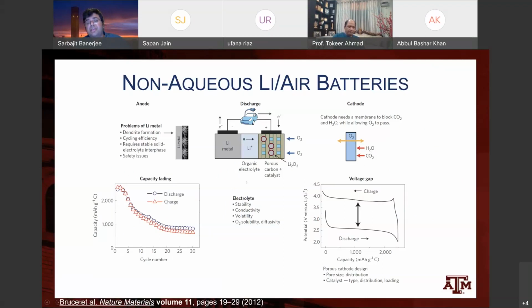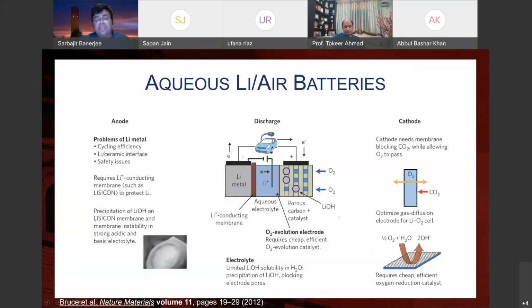This is another need, and then having an electrolyte that is stable, conductive, and where you can address issues of oxygen solubility and diffusivity. So this remains a problem. And then aqueous lithium air batteries, again, are very attractive, where you can think about going back and forth between lithium metal and lithium hydroxide. But again, you need to have an efficient oxygen evolution reaction catalyst. This has been a problem because most of the oxygen evolution reaction catalysts are again precious metals. Some of the same challenges we talked about when we were talking about hydrogen fuels.